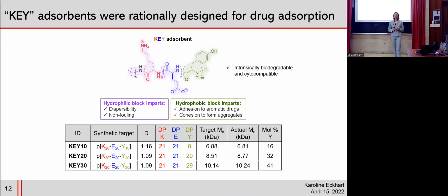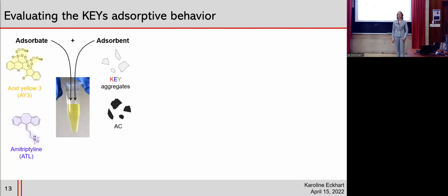We made a series of 3 keys, and because we were using NCA-ROP to make these, we have incredible control over the amino acid composition. We also have low dispersity, and we made the keys with 3 different ratios of the hydrophobic block. So key 30 has the highest amount of hydrophobic, and key 10 has the lowest amount of hydrophobic. And we sought to analyze how these materials adsorb different model drug compounds relative to the clinical standard activated charcoal. So to do these experiments, we combined a known concentration of the adsorbent, which is either the key aggregates or the activated charcoal, with a known concentration of the adsorbate. This is the thing that's going to be adsorbed.